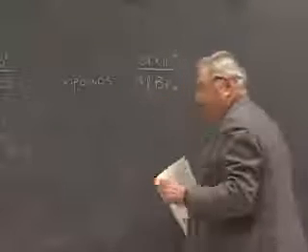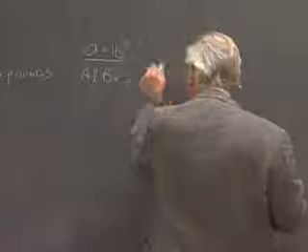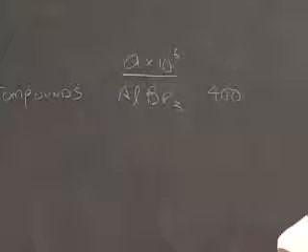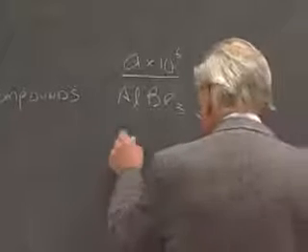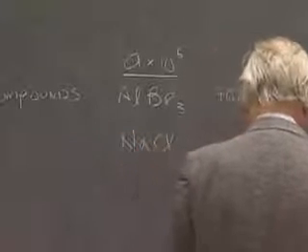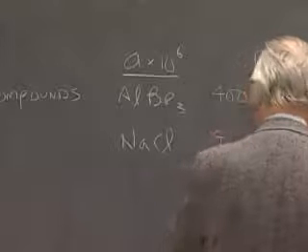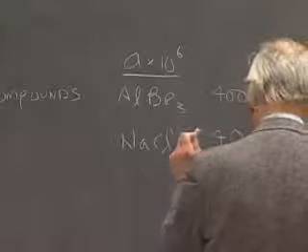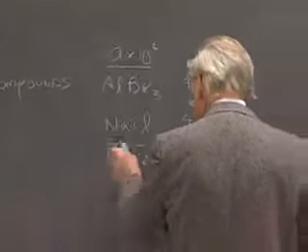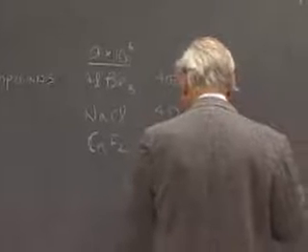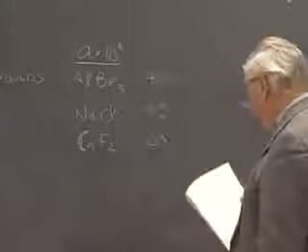For aluminum bromide, hardly a high technology material of commerce, but it's in my list because this has one of the largest linear thermal expansion coefficients of any material, very weakly bonded compound. For a more typical ionic compound, NaCl, 40 times 10 to the minus 6. For calcium fluoride, this has a divalent cation in it, so the material is stronger. It's more strongly bonded, 20.